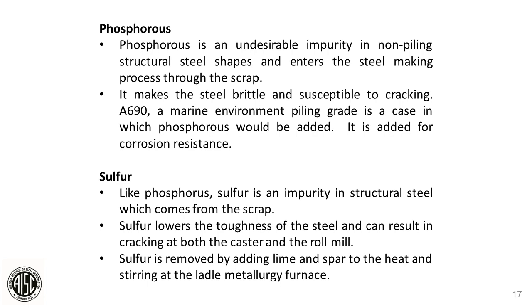So, phosphorus. Typically, phosphorus is an undesirable impurity in non-piling structural steel shapes. We do our best to minimize that. There is one exception, ASTM A690. It's a marine environment piling grade. It's a case in which phosphorus is added intentionally for corrosion resistance, but it negatively impacts toughness. And sulfur, again, sulfur is something we try to get rid of in the steel. We try to process that out, and we'll explain that. It's an impurity, lowers the toughness of the steel, and it's removed by adding lime and spar at the ladle metallurgical furnace to be removed. And we'll explain how that process goes next. Next slide, please.